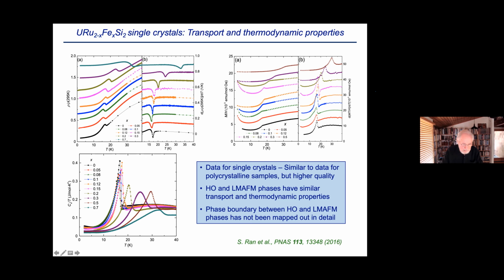And then this is what happens to the specific heat divided by temperature versus temperature itself. Down here you see sharp hidden order transitions, then they get more broad when you get into the antiferromagnetic phase. But interestingly enough, the hidden order and large moment antiferromagnetic phases have similar transport and thermodynamic properties, although you do see differences, but they're similar. Anyway, there's still more work to be done to map out the phase boundary in more detail.